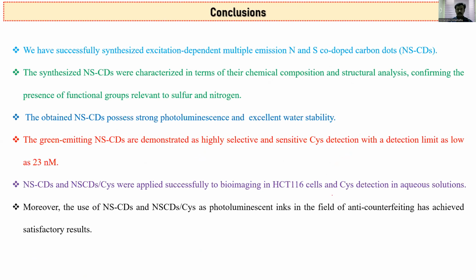The conclusion of this research work: we have successfully synthesized excitation-dependent multiple emission, nitrogen and sulfur co-doped carbon dots. The synthesized materials were characterized for chemical composition and structure, and the presence of functional groups relevant to sulfur and particularly nitrogen. So we can get nitrogen and sulfur carbon dots that possess strong photoluminescence and excellent water stability. The green emitting carbon dots demonstrated highly selective and sensitive cysteine detection, importantly in aqueous solution without any solvent addition. Moreover, we can use these carbon dot complexes as photoluminescence ink with satisfactory results. Okay, this work I have also published in Microchemical Journal in 2021.